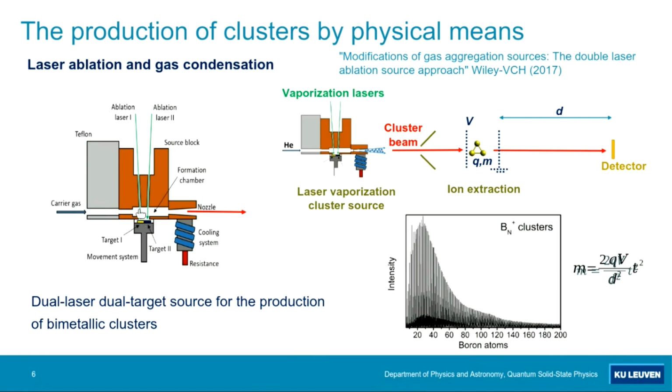So the atoms of the plasma, the metallic atoms, will interact with the helium gas. It will not form a stable metal-helium complex, but the helium will actually take this kinetic energy away, and then these metallic atoms will condense into particles.